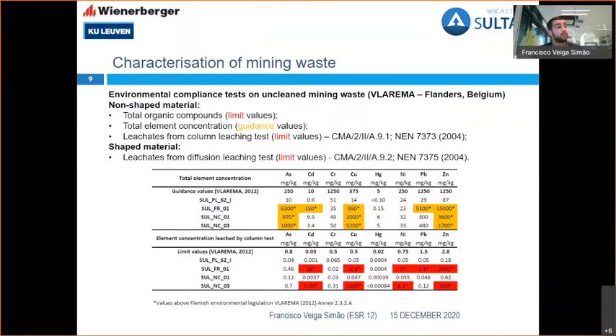The total element concentration values are guidance values. So this means that if it is exceeded, and you will see that here, some of the materials, as I mentioned, Freiberg and Neves Corvo, overcome the established limit. Nevertheless, you have a second test, a second chance, let's say, to do a column leaching test on this granular material. And if the material passes this test, it can be considered for use as a granular material for road constructions, field embankments, field dams, etc.